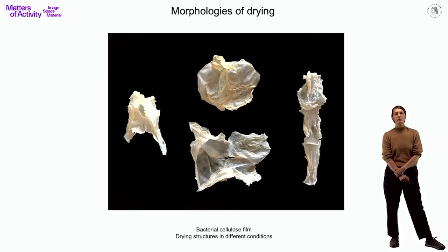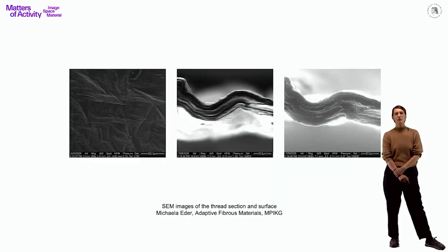And in these examples, we can see that all the initial elements are simple and all the same, and just connecting them in the wet state and exposing them to various drying conditions results in highly complex morphologies. The scale of the transformation is actually microscopic, so all these changes happen on the level of the fiber. The swelling process causes the biofilm to temporarily become gelatinous and then reverse to the dry state in which the fibrous structure reappears.